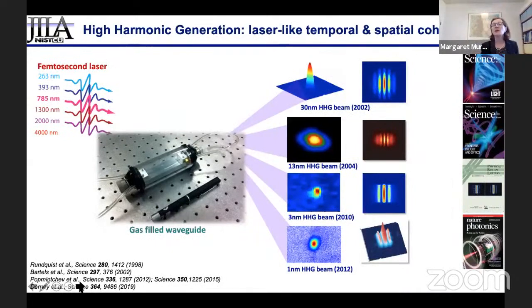So what do we do for high harmonic generation? What we do is we take femtosecond lasers, which are relatively straightforward to implement these days in the ultraviolet or near infrared or mid-infrared region of the spectrum, and focus them; in our group, we use gas-filled waveguides. And then if we tailor the color of the femtosecond drive laser, we can generate short wavelength beams that span from the vacuum ultraviolet to the extreme ultraviolet to the soft X-ray region.